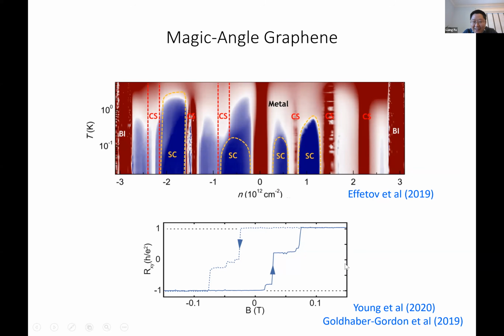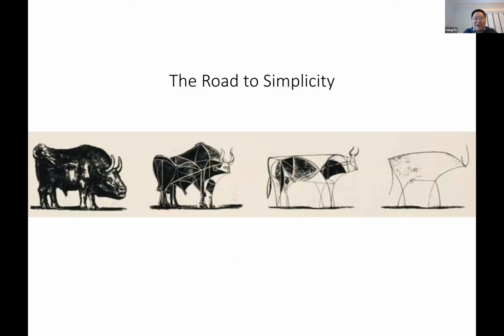And even more surprisingly, again with this work coming out very rapidly, it appears that when the magic angle graphene is aligned with the boron nitride substrate, an integer quantum Hall effect appears without any external magnetic field, the so-called Chern insulating states. And this is totally different from the case of cuprates. So with this, the talk is neither about cuprates nor about twisted bilayer graphene.